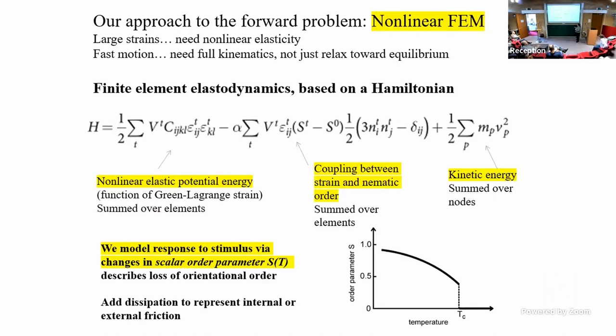Here's a typical graph of scalar order parameter versus temperature. In the nematic range, the material starts pretty well ordered and it disorders, and then right at the nematic-isotropic transition, that order goes to zero. But it's not sudden, it goes a little bit. So as you change the temperature, the material is going to change shape. It's also possible that you can affect the scalar order parameter by shining light, by changing the chemical environment, all those other things. So this is my control parameter.